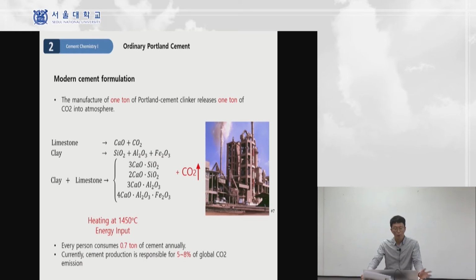So let's take a look at the formulation of the modern cement, OPC. We have to mix clay and limestone together, and we have to burn that kind of mixture at a very high temperature, such as 1450 degrees Celsius, in a very huge quantity. So we can imagine this is very difficult to uniformly burn such a huge quantity of materials. This is definitely a technical challenge, because in some regions the temperature is supposed to be higher than 1450, and some regions inevitably will be lower than 1450 degrees Celsius. Anyway, we have to heat this mixture, clay and limestone, at very high temperature, and we can gain this kind of material.